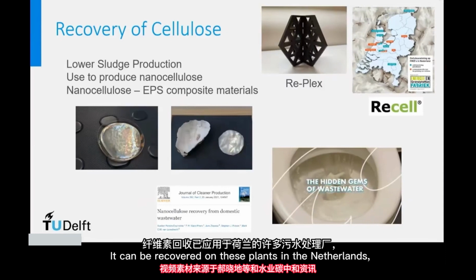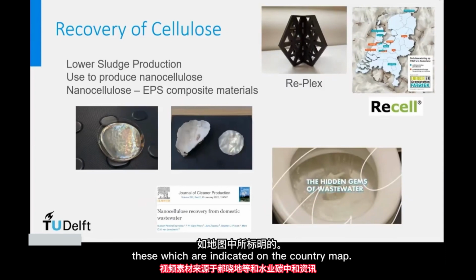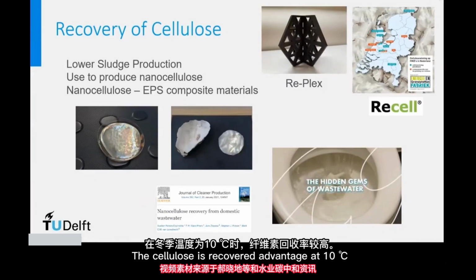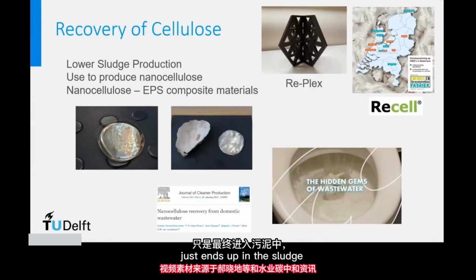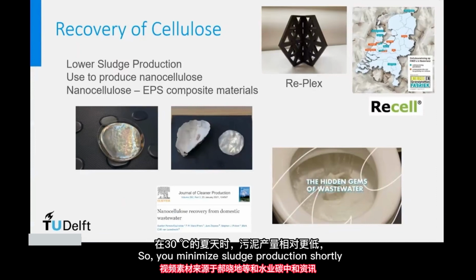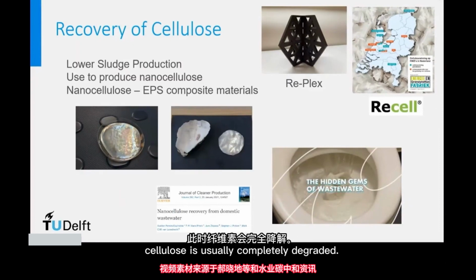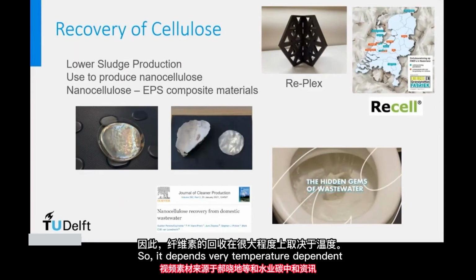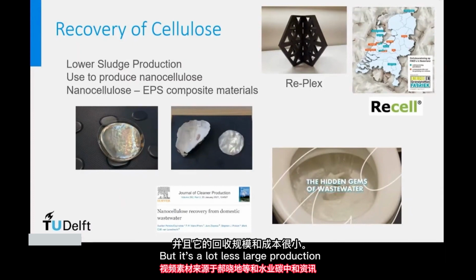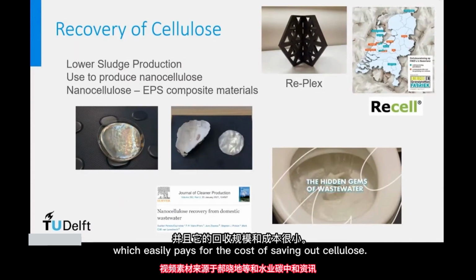On these plants in the Netherlands, which are indicated on the country map, the cellulose is recovered. Advantage: at 10 degrees Celsius, in the winter temperature in the Netherlands, cellulose is not degraded, it just ends up in the sludge, and it contributes to the sludge production. So you minimize sludge production, certainly in the winter, and a bit less in summer. At 30 degrees, cellulose is usually completely degraded. So it's very temperature dependent how efficient it is. But it's a lot less sludge production, which easily pays for the cost of sieving out the cellulose.